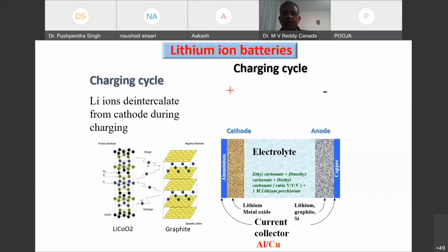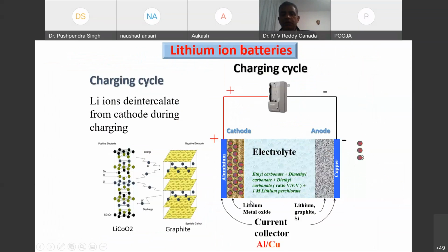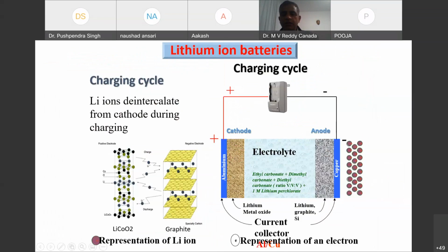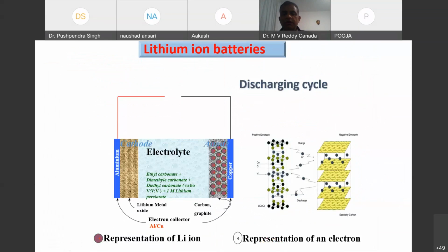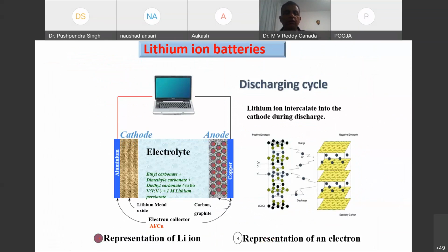Again, what I discussed are some diagrams. So again, exactly this is the way the lithium will move inside with both structures, for example, lithium cobalt oxide and graphite. Similarly, during discharge, whatever lithium is coming from here will go back to the original state. That's why we call it the rechargeability. Still, during the first cycle, a small amount of lithium is stuck in the layer. So that's why we call it the irreversible capacity in the first cycle.